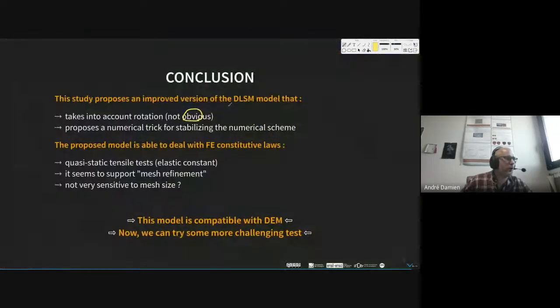So now the conclusion. This study proposed an improved version of the DLSM model that takes into account rotation, that proposes a numerical trick for stabilizing the numerical scheme, and the proposed model is able to deal with constitutive laws. We tested quasi-static cases, elastic material, plasticity, orthotropic material, and quasi-brittle material. It seems to support also the mesh refinement, and I think that this is not very sensitive to the mesh size, but it's not so clear.